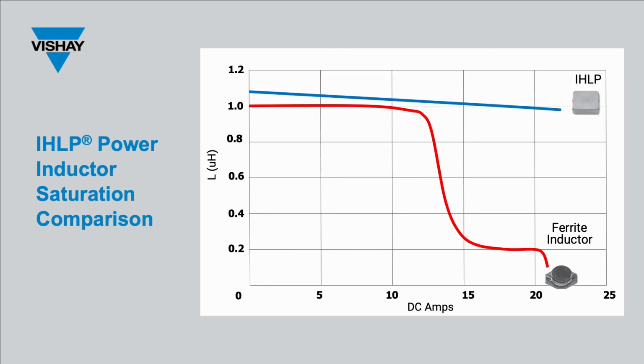It should also be noted that even though the powdered iron IHLPs do not hard saturate, we still define a saturation current rating on all of our data sheets. Since the inductance does decrease to some extent as the current increases, we define saturation as the DC current that will cause the inductance to drop approximately 20% from its initial value. We also provide the inductance versus current graphs for each value on all of our data sheets.